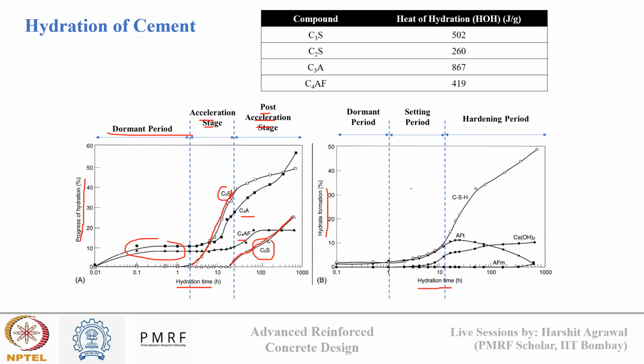So you can see initially in the dormant period, there is a very small quantity of hydration product formed, which is mainly a small amount of CSH and alumino ettringite, formed due to the reaction between C3A and gypsum. Okay, in the setting period, where we see a little stiffening in concrete, there is more CSH and ettringite formation taking place. And then in the hardening period, this ettringite starts to convert into monosulfate if the gypsum is completely consumed and still there is C3A present in the system, while there is an increment in the growth of CSH, and CH also starts to form, that we saw in the hydration of silicates. Okay,